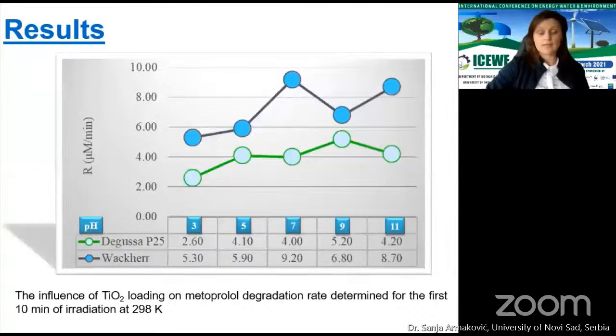Taking into account that the isoelectric point of the catalyst is around 6 and the pK of metoprolol is 9.7, within the interval of 6 to 9.7, electrostatic attraction is favored between the negatively charged catalyst surface and protonated metoprolol, which explains higher degradation efficiency at the mentioned pH 7 and 9. The speed of degradation is different for each catalyst. And what happened for the pH value of 9 in the case of Wacker still remains to be explained.